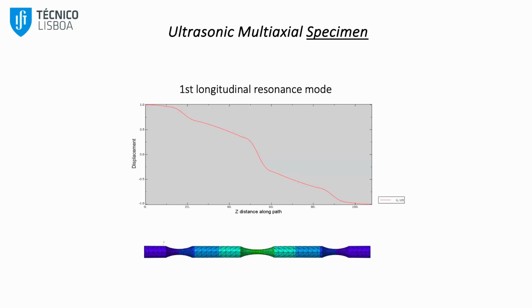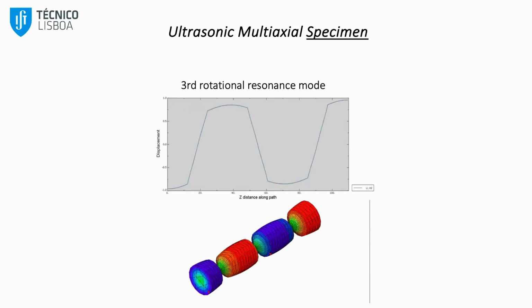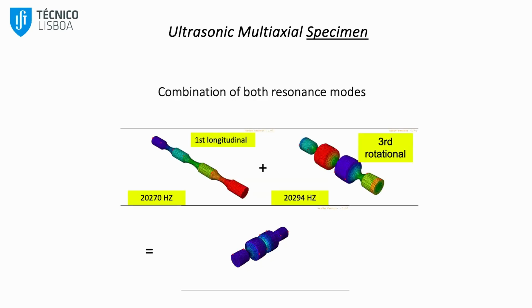But if it works, you will see that this part here is a node. So displacement is 0, which means we are going to get the higher stresses here. And if we move to the torsional component, we have 3 throats, as I said before, and also 3 nodes, okay? So 0 rotation here, and also 0 rotation here, which means that when we combine both, we are going to reach the first longitudinal resonance mode, the axial one, around this.